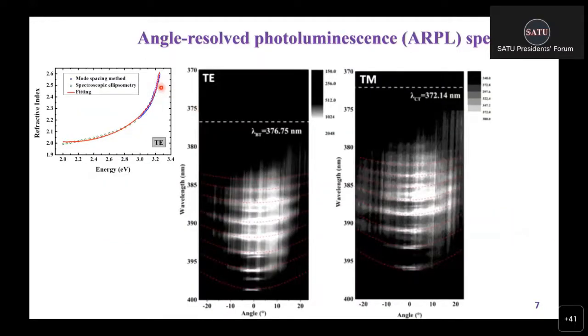When we obtain the index dispersion, we can use it to predict the curvature of the energy dispersion on the CCD device. The prediction is the red dashed lines, and the white signals are the observations. You can see that the prediction fits the observation very well.